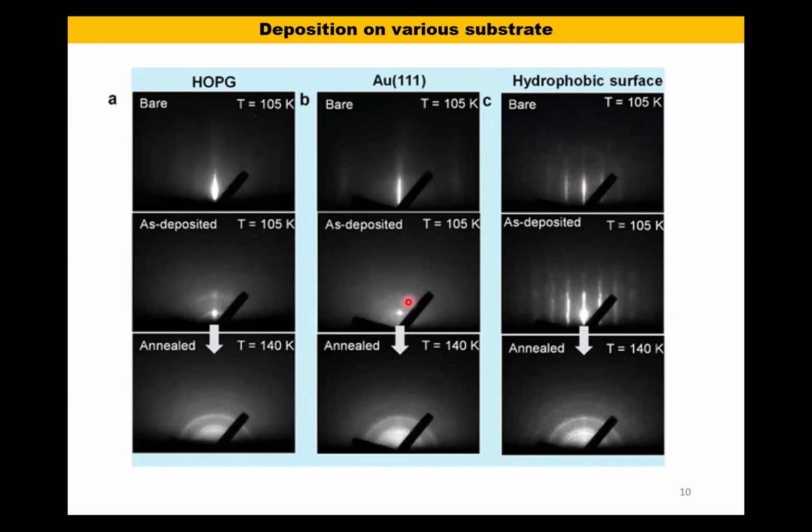When we deposited the amorphous solid water and THF, we saw these THF crystallites. You may wonder why we see different kinds of diffraction patterns when depositing the THF and water ice matrix. This is due to different types of deposition. In this particular case, THF and water are in the exact ratio. You can see some THF and amorphous solid water. In this case, more water molecules were deposited on the surface. As you know, RHEED is very specific to the surface, 1 to 5 nanometers.